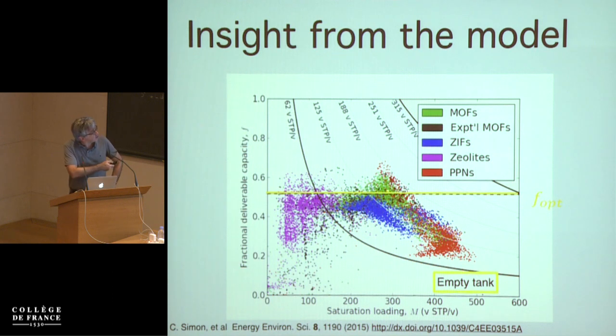But why are the materials above the optimum line? It's not only important that you have the optimum methane wall interaction, but also methane-methane interaction. A methane molecule can recruit another methane molecule, and then you can get above this limit. But that is a detail. So here we used an application in which we didn't discover a material, but we basically said to the experimental people, you already have the best material, and that's here. So stop further trying, just develop the materials you have.